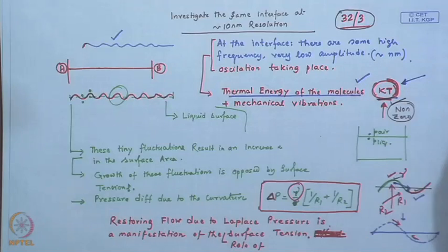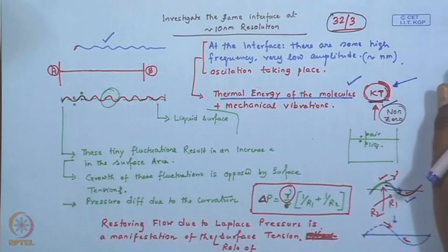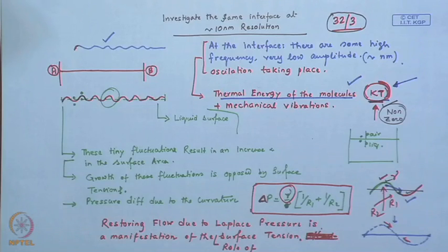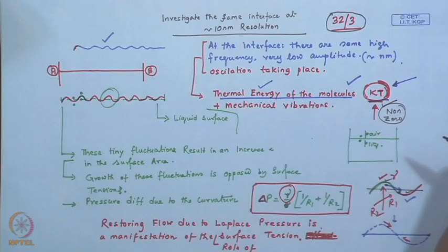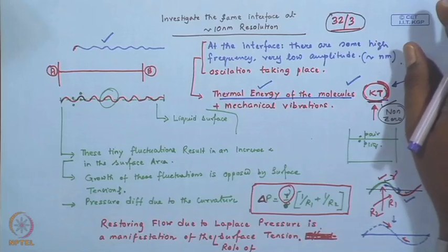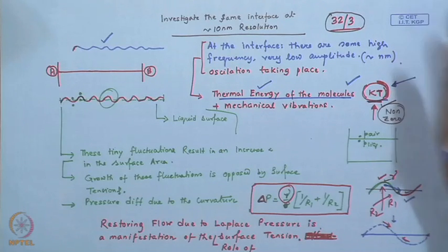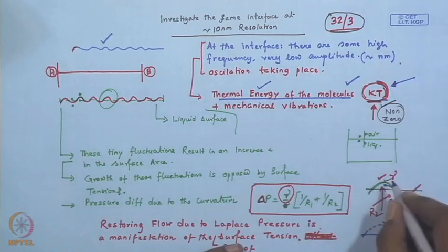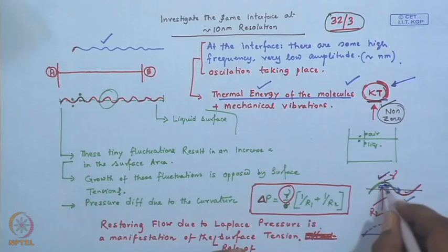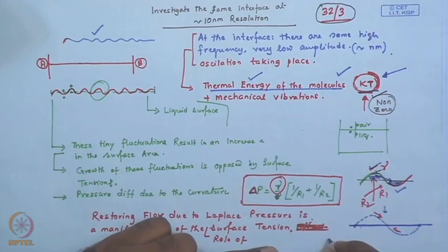Consequently, there are these very tiny high frequency, low amplitude oscillations which are always present on the surface of the interface, and the moment these fluctuations set in, surface tension opposes the growth of these fluctuations. So, you have a dynamic equilibrium prevailing on the surface of the film. The essential features are that this is triggered by the thermal fluctuation and opposed by the restoring effect of surface tension. These fluctuations also give rise to a non-planar liquid surface, so there is a localized spatial variation of Laplace pressure along the surface of the film, which results in flow of liquid from the peaks of the fluctuating surface to the valleys, restoring the film back to its original flat morphology.